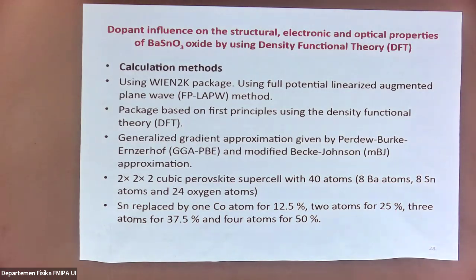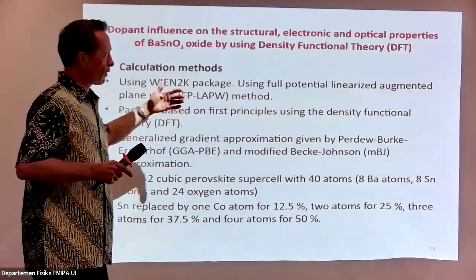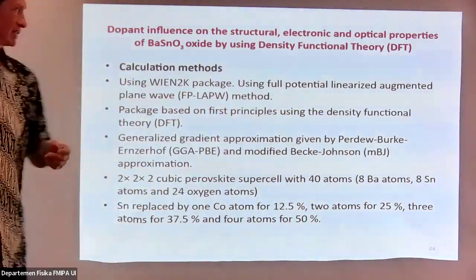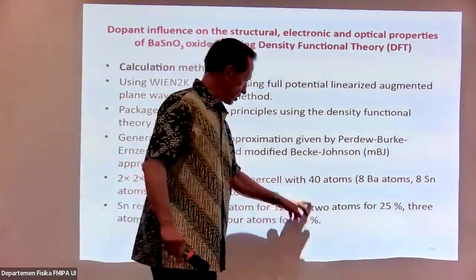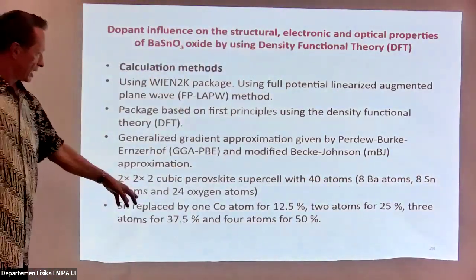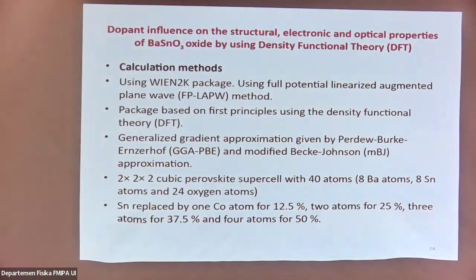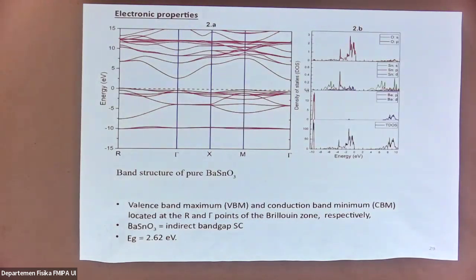But nevertheless, computing is interesting because it shows you the possible interest of some doping. We see here, for this variant material, we doped it with cobalt. And simulation is also limited in the way you choose a doping rate. So here it was only possible to choose 12.5, 25, 37.5, and 50% of cobalt. But you will see that nevertheless that was interesting.